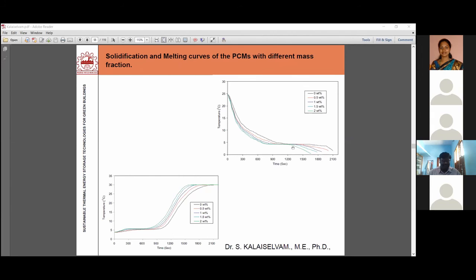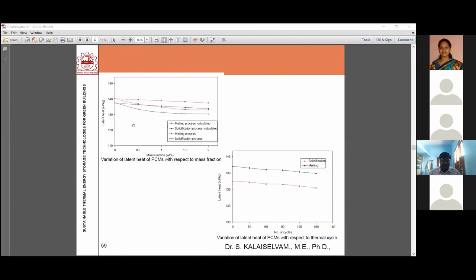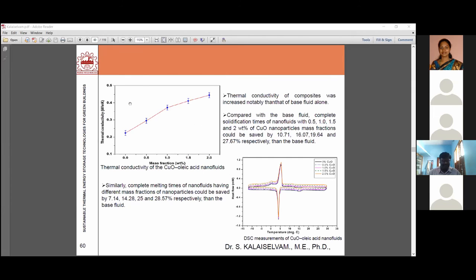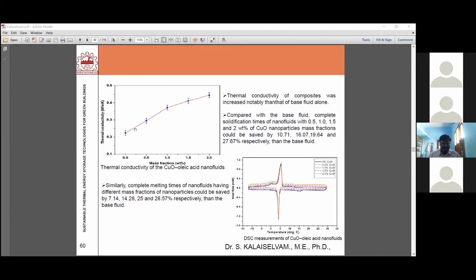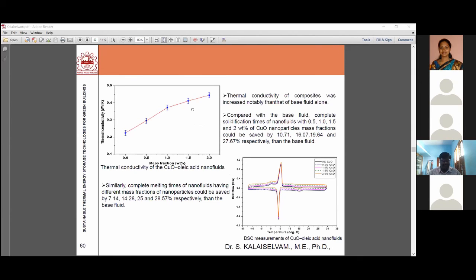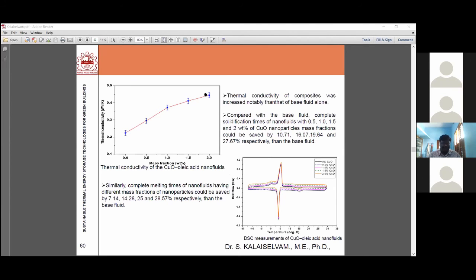So here, if you look at that particular solidification and melting curve, the solidification and discharge time reduces. And by adding this nanomaterial, there is a slight change in the latent heat, which is also acceptable to the research community. You may wonder why the solidification reduces. For that, there is evidence stating that by adding this nanomaterial, the thermal conductivity of that particular fluid increases. Without nanomaterial it is lower; by adding this nanomaterial, your thermal conductivity increases.